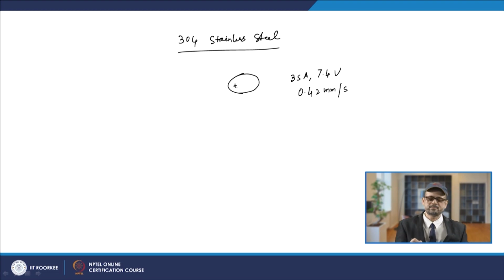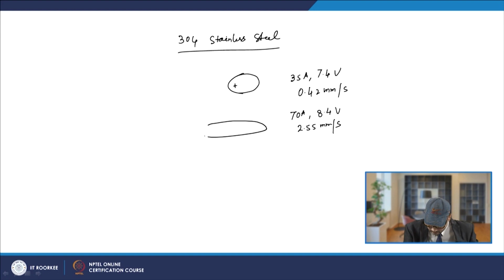So, this is the tip of the electrode. And as we discussed, here we are increasing the Q also, like the heat input, and that will depend upon the current and the voltage. So, if you increase this to 70 ampere and the voltage is increased to 8.4 volt, and also the velocity is increased to 2.55 mm per second, in that case your pool will change, and it will appear like this. So, in this case this is the direction you are doing the welding.